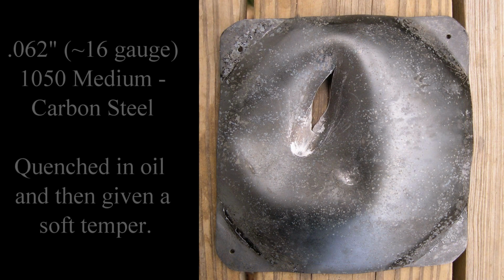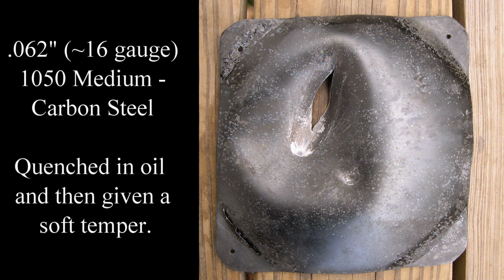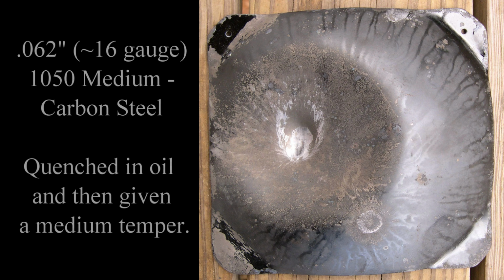This next piece was heat-treated with a soft temper, and you can see that the musket ball still penetrates but with far less energy. The steel is still a bit on the soft side and is actually torn under the force of the impact. The third piece was heat treated with a medium temper, and we were pretty surprised to find it actually completely stopped both shots. While the musket ball has made a mess of things, the dueling pistol doesn't even leave a dent.